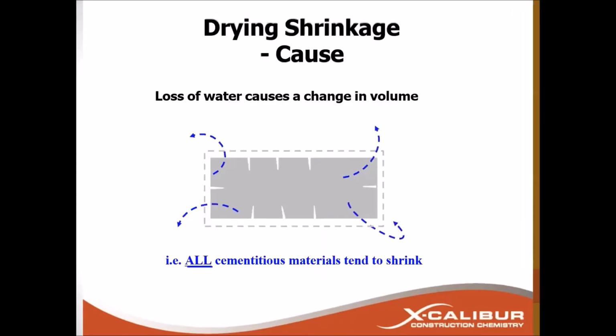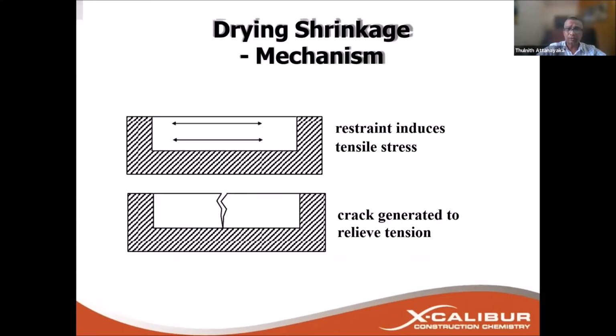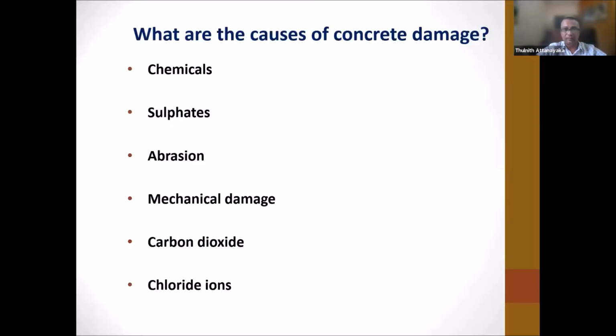So we talk about drying shrinkage cracks. The cause of drying shrinkage is that loss of water causes change in volume. I highlighted this: all cementitious materials tend to shrink. In this drying shrinkage mechanism, restraint introduces tensile stresses, so obviously cracks are generated to relieve the tension.